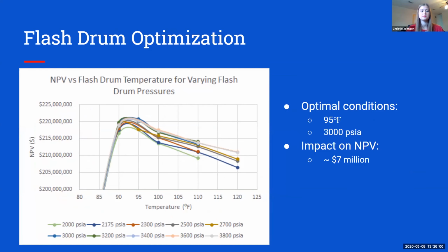We also optimized the flash drum that we used to separate out the unreacted hydrogen after the reactor so that we could recycle that. Optimizing the flash drum, we found that a pressure of around 3,000 psia and a temperature of 95 degrees Fahrenheit were the optimal conditions, and that kept the hydrogen mostly pure. Some propane did get leaked into the hydrogen, but we continued to monitor our kinetics, and that didn't seem to affect how our reactions were proceeding.